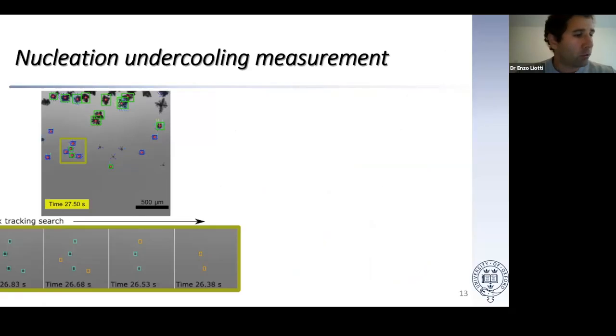The nucleation undercooling essentially is the driving force that is necessary for a grain to form. So these nuclei sit already in the liquid above the melting point. When the temperature of the liquid is decreased below the melting point, there is still some energy barrier that needs to be overcome for these nuclei to form a grain. And this is very important to understand how nucleation works and how it can be improved.